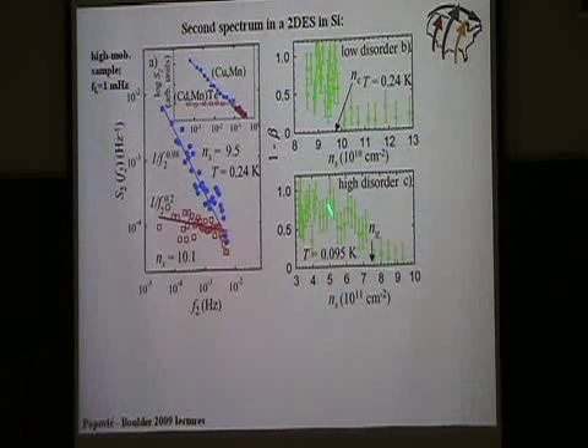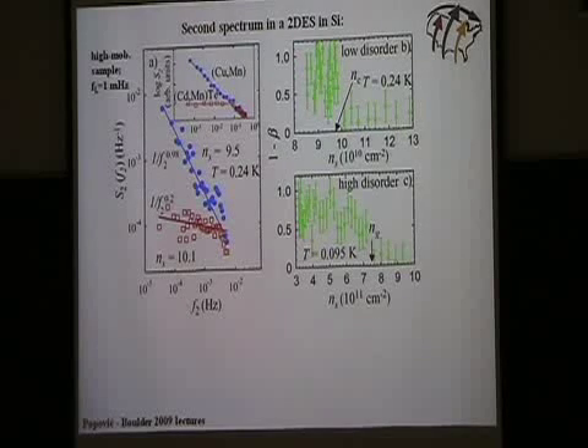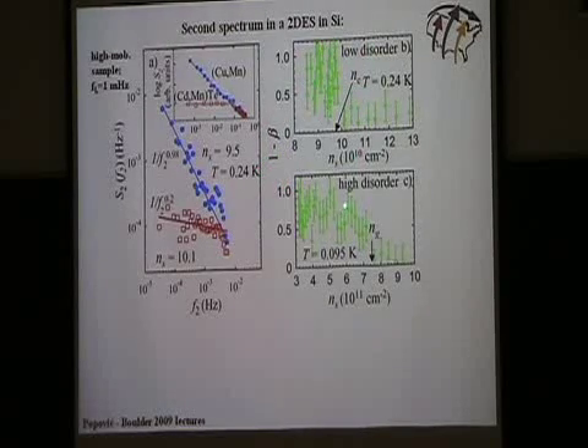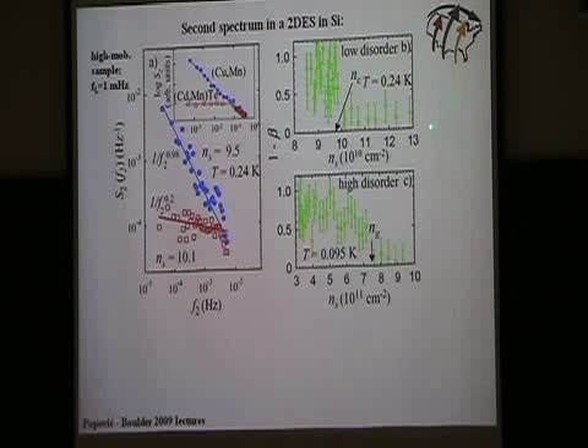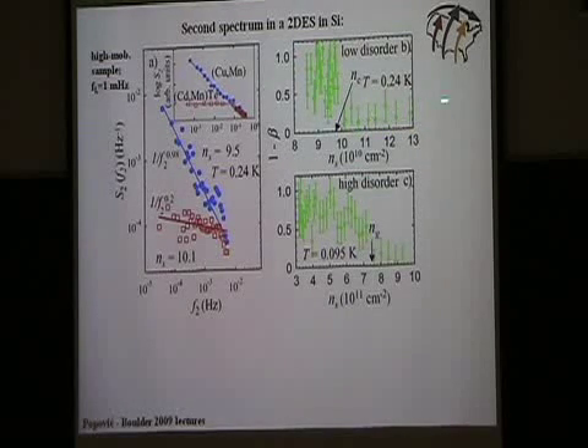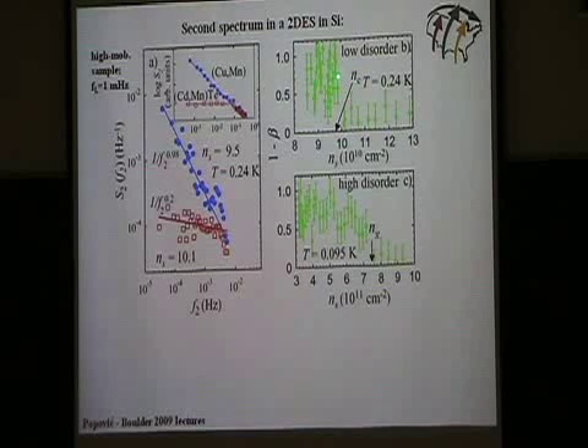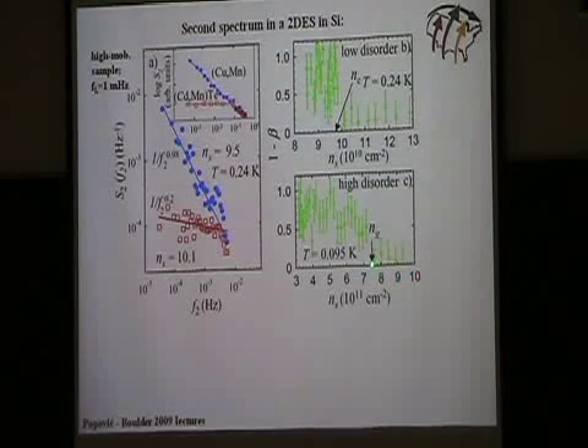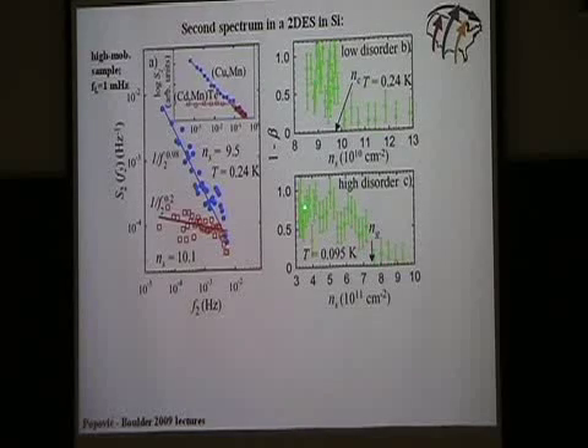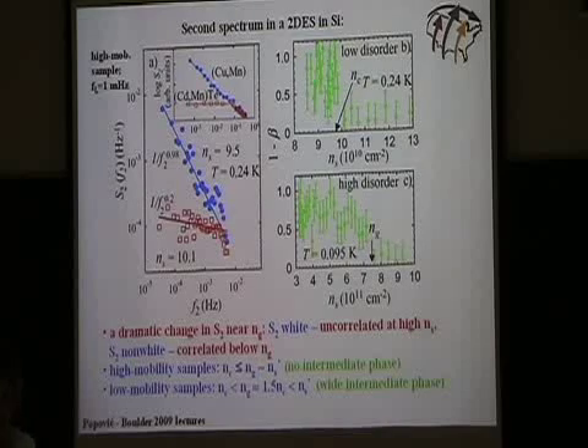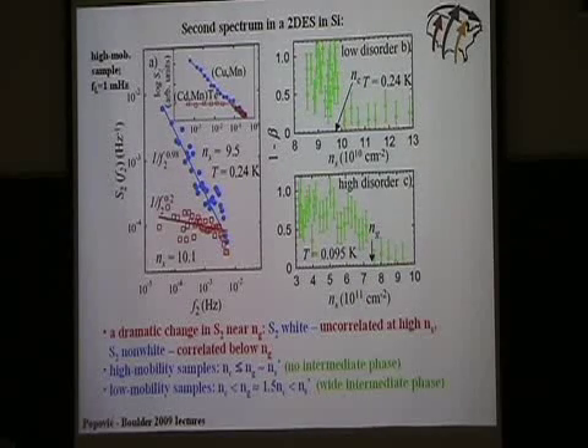So we've done that, and this is just an example, a couple of second spectra for two different densities. The main result is here. This is the value of 1 minus beta, the measure of correlations, for two kinds of samples. In samples with high mobility or low disorder, this is 0. So the noise, which we already saw just by looking at the data was Gaussian, has no correlations. And then at the density, which more or less is the same as NC, we see that the noise becomes correlated. And similarly, in low mobility samples where we have this intermediate metallic glassy phase, at high densities there are no correlations. This is Ng, and below Ng, we start seeing the onset of increasing correlations. So everything fits nicely. At the same density where the dynamics become slow, it also becomes correlated.